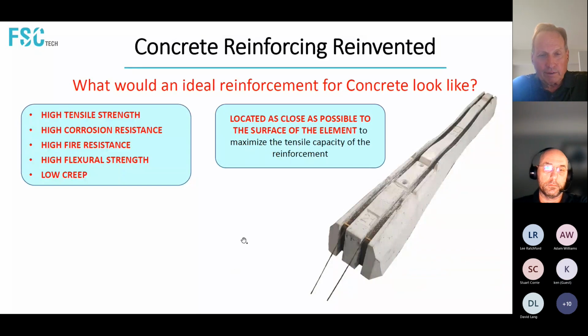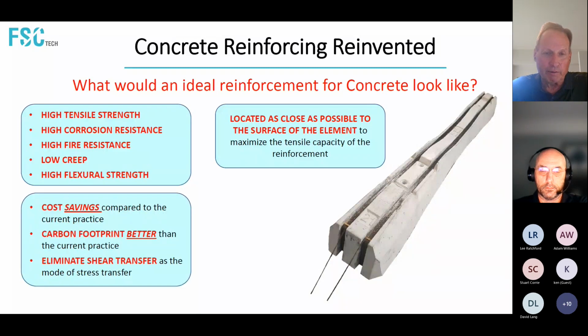You'd want to locate the reinforcement as close as possible to the surface element because this maximizes the tensile capacity of the reinforcement itself. So you can have a very strong, high tensile strength material, but you have to keep it away from where the tensile stresses are highest. You just have to use more of it.